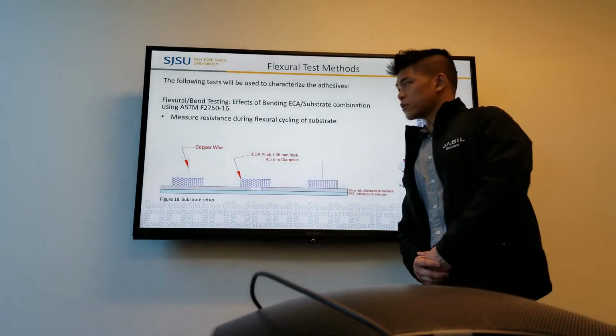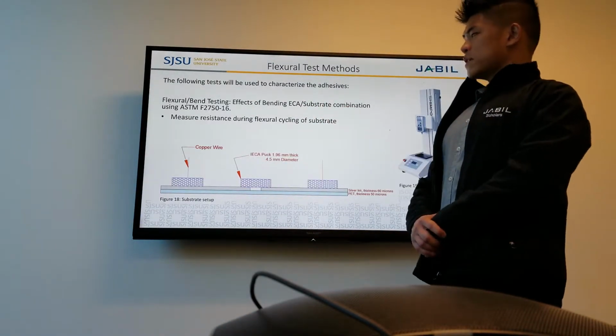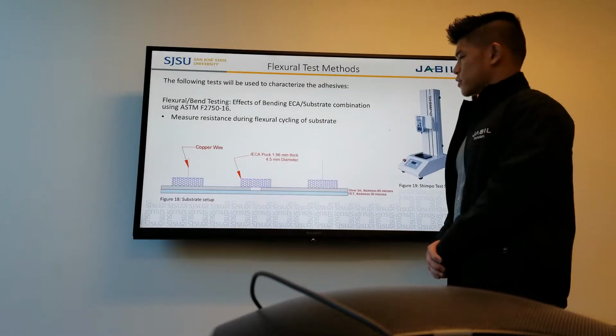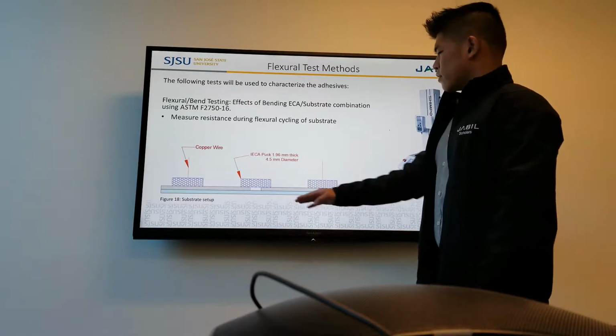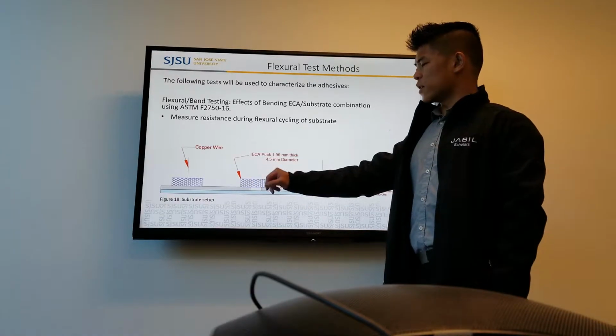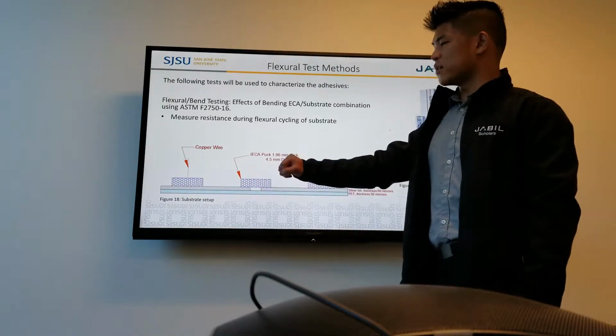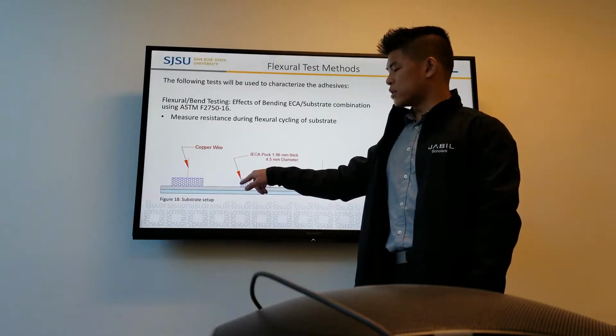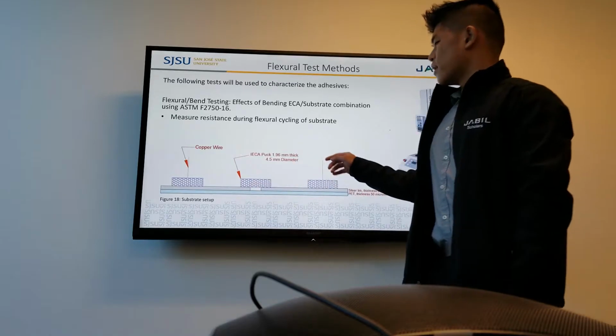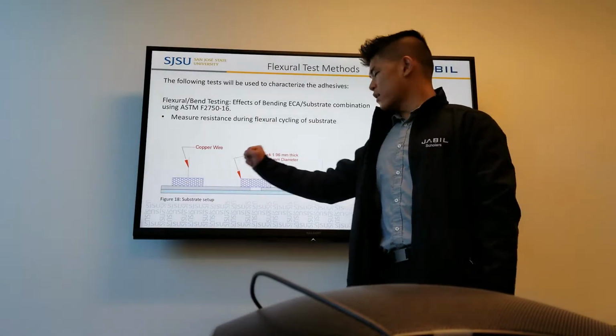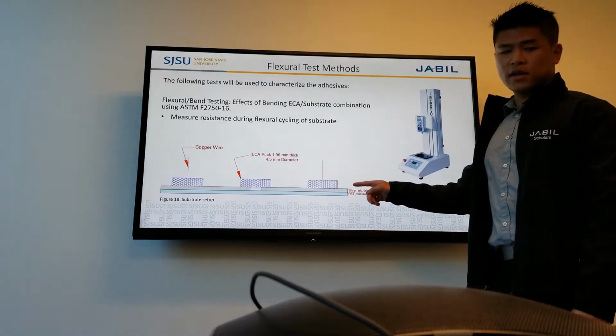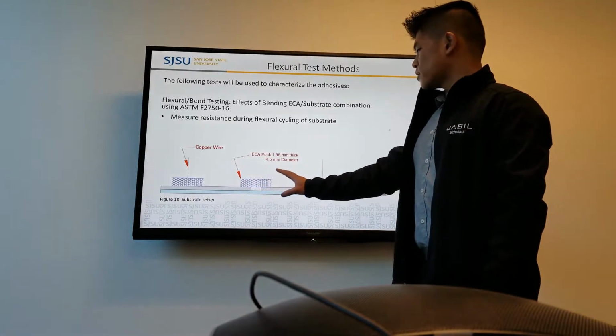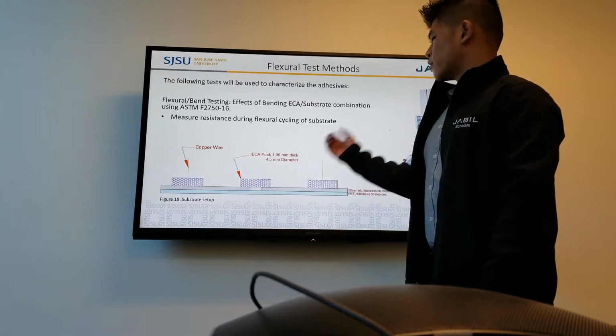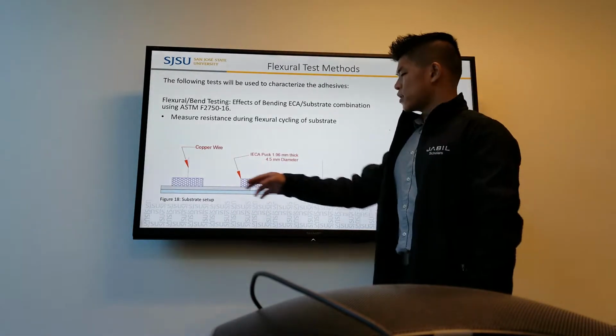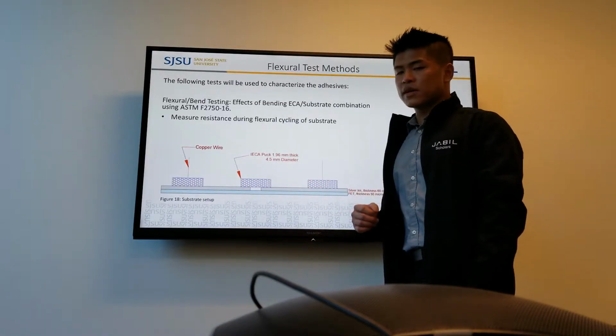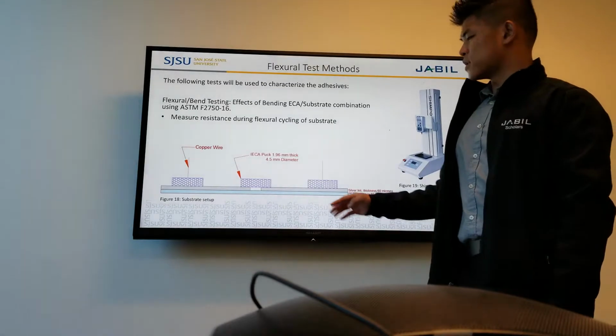In our last test, the Flexural Test, we followed ASTM F2750 to measure the resistance during flexural cycling of the substrate. Here's the setup of the substrates. PET is the bottom layer, and then you make 2 silver ink layers with a bridge in the middle to be bridged by the adhesives. Adhesives in the middle will bridge the circuit and finish the circuit, and then you put copper wires in these adhesive pucks on the side to be able to measure the resistance with a data logger. The size of the pucks is 4.5 millimeters in diameter, and they're 1.96 millimeters thick. The placement of these adhesive pucks on the ends does not matter because you're measuring the change in resistance over time, not the resistance of the circuit itself.